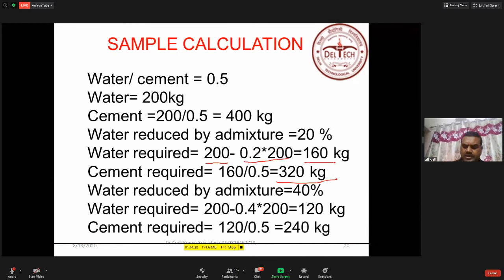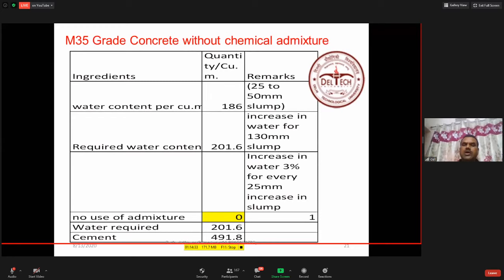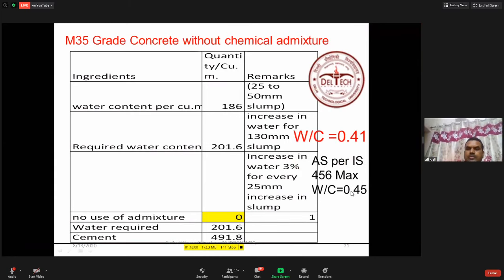Now, with the help of an example from a site, I will just explain what we have done. Okay, we required a slump of 130 for a project, and we required to design the M35 grade of concrete. So if I am using 130 slump, I required 201.6 kg of water. Okay, as IS code says, the water cement ratio cannot be more than 0.45, and for practical purposes, I have used the water cement ratio of 0.41. So if 201.6 kg water is required and the water cement ratio is 0.41, then the cement required is 491.8 kg.